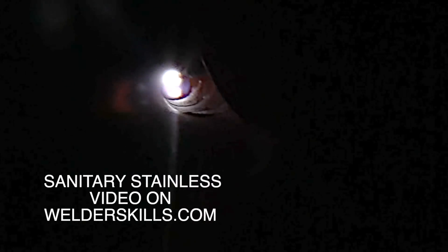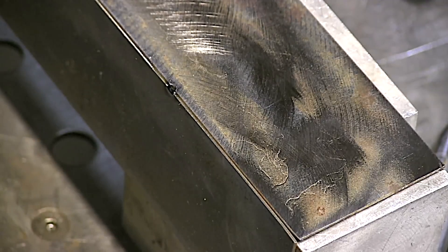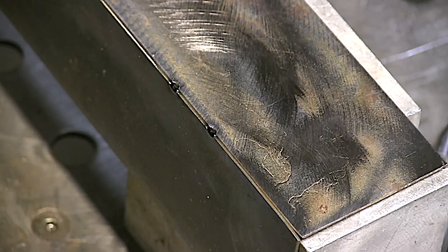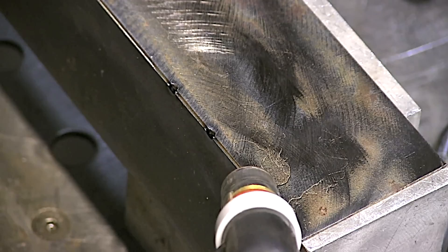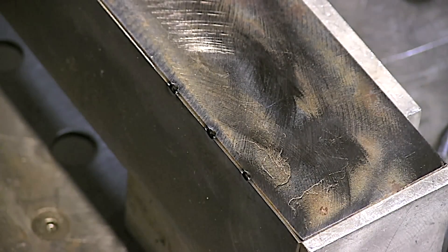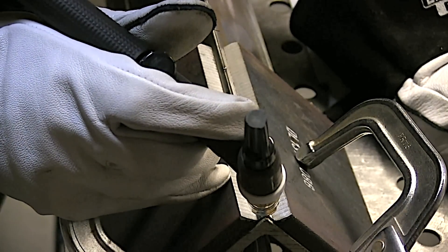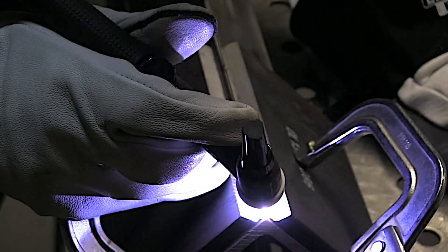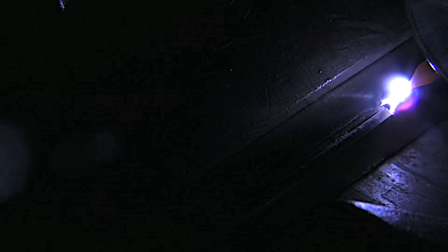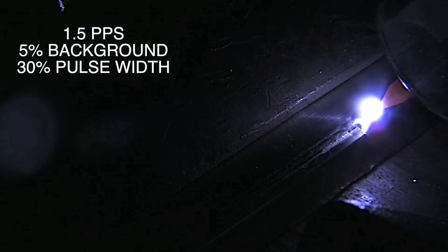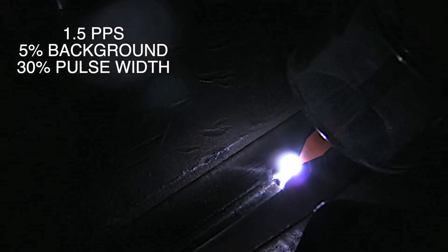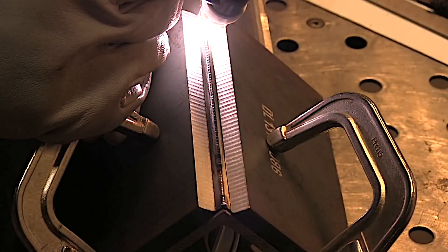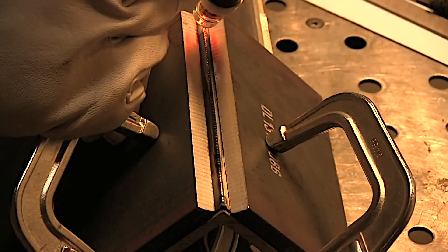Another joint that's often done autogenously is an outside corner joint on something like 18 gauge stainless. And here you can use that same technique for flash tacks, but you got to have no gap—that's the key. Chill bars also help tremendously. I don't have them clamped quite as closely as I could have them right here, but they're still helping to pull a lot of heat out and preventing distortion. Got a really low background current here with one and a half pulses a second. But notice how that clear cup just kind of really glows and lights everything up—really helps you see where you're going better.